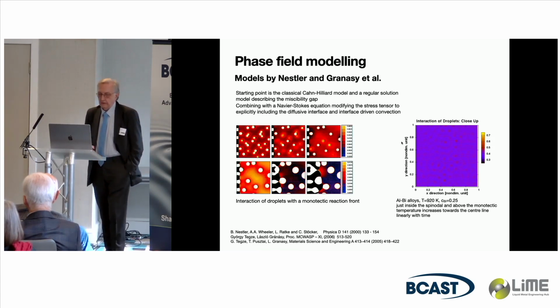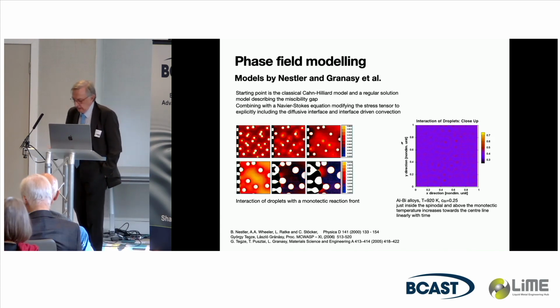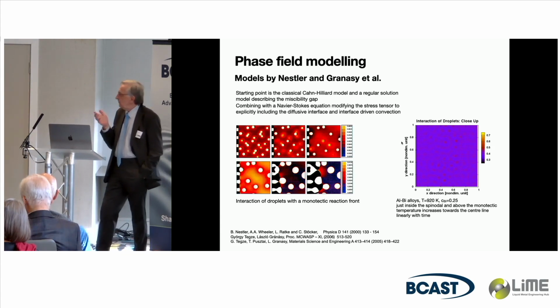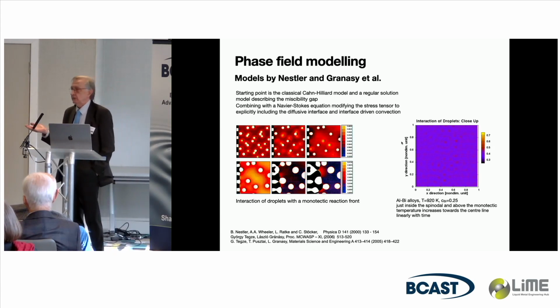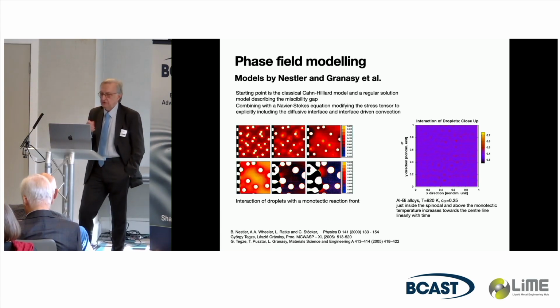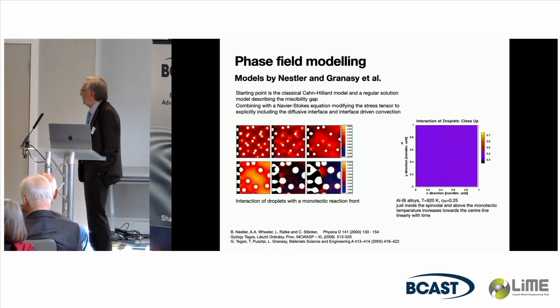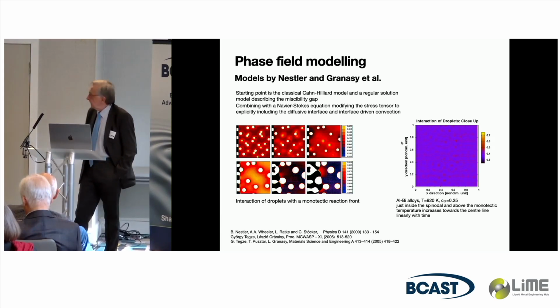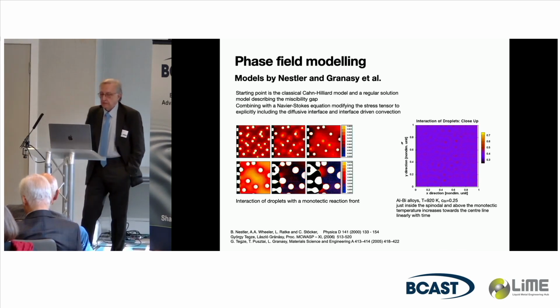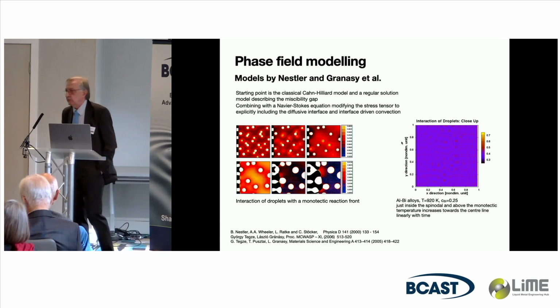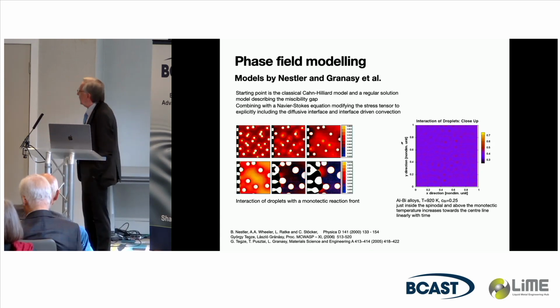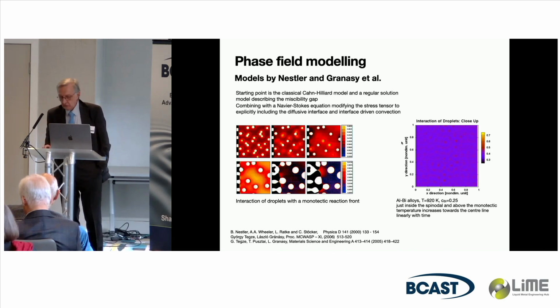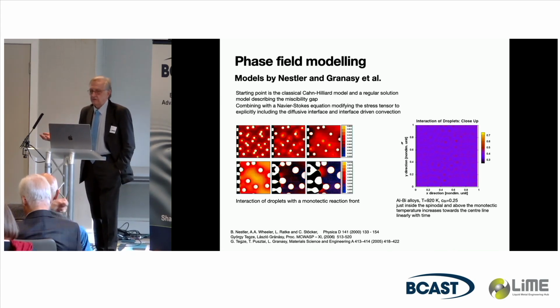The point is, well, yeah, okay. In the 90s, it came up, end of the 90s for us: isn't it possible to use a phase field model and combine it with convection? Up to that time, people studied dendritic solidification, etc., with phase field models, but convection was a difficulty. And we did that with Adam Wheeler and Britta Nestler, now at Karlsruhe Institute of Technology. And we combined the Cahn-Hilliard equation with the Navier-Stokes equation, taking into account, however, that you can explicitly include interface-driven convection. You had to do an extensive stress tensor in the Navier-Stokes equation.